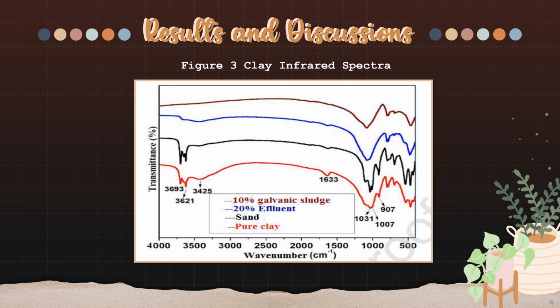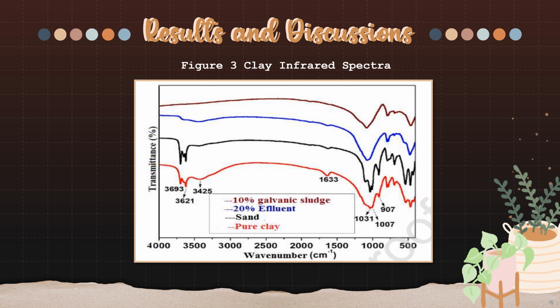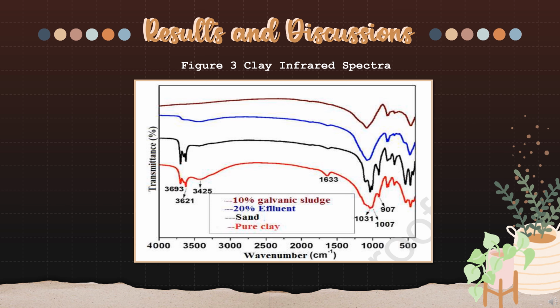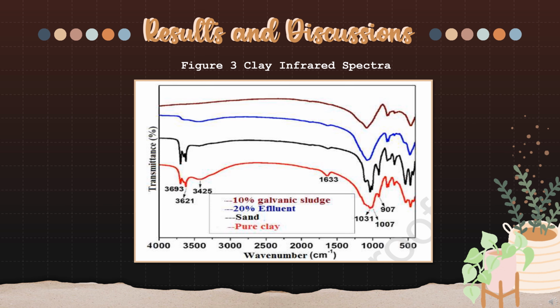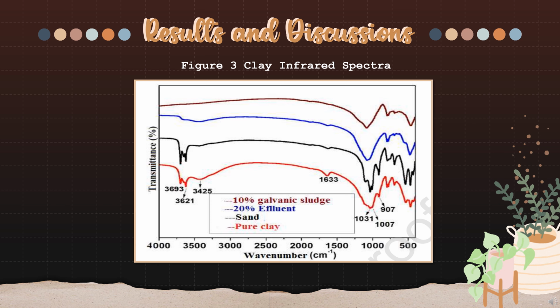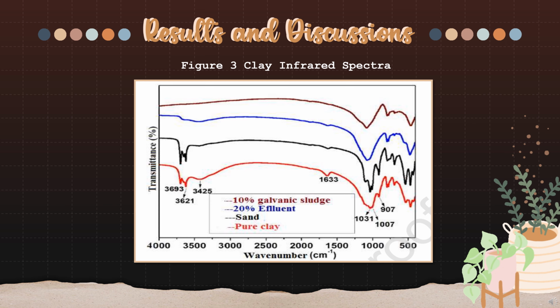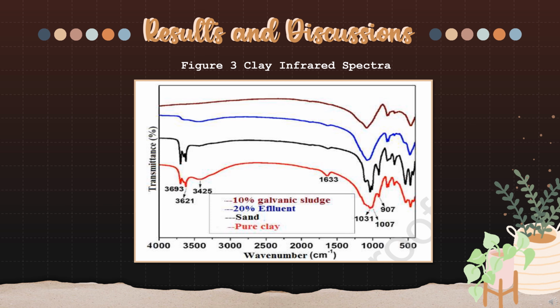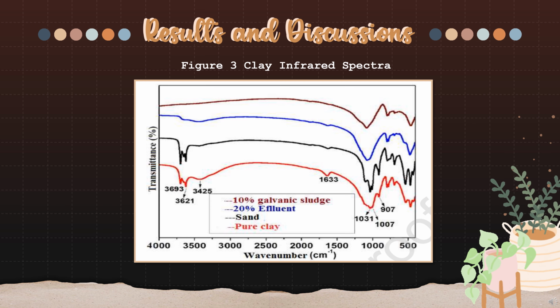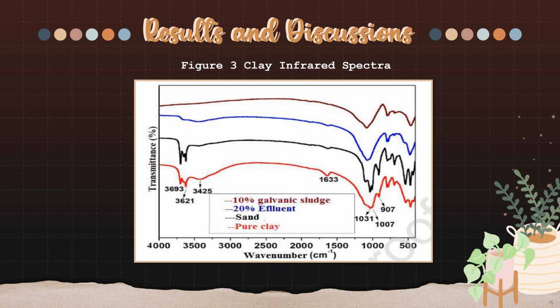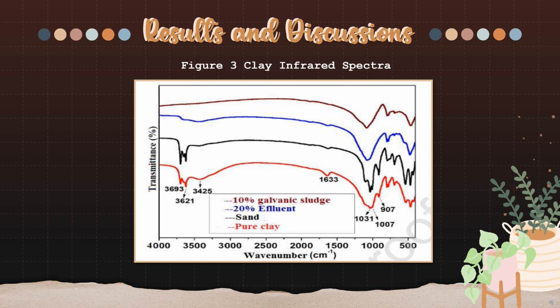Since the samples were subjected to a calcination process at around 600 degrees Celsius that encourages the removal of the absorbed water molecules, bands 3621 and 3693 per centimeter disappeared in samples with 10% galvanic sludge and 20% effluent. The vibrations of asymmetric elongation between silicon and oxygen in the silicate tetrahedral structures are expressed by the absorption bands of 1031 and 1007 per centimeter. Deflection vibration between aluminum and hydroxyl in phyllosilicates causes the 907 per centimeter band to appear.